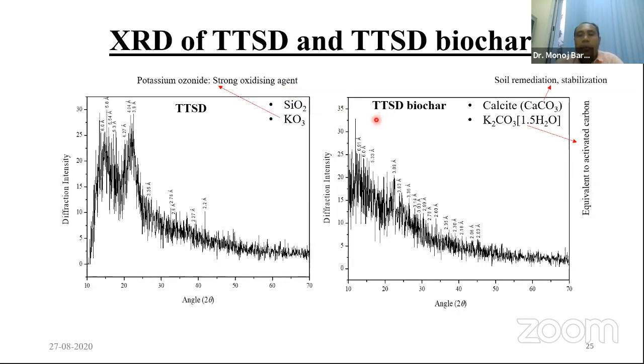And similarly, if we see the XRD spectrum of the biochar obtained from this TTSD biomass, then here again we do not have any crystallinity nature. So this is basically the amorphous kind of nature, and also based on some peaks obtained at different d-spacing values or different Bragg's angles, we can identify some elements, something like calcite, which is very much useful for soil improvement if we apply it for agricultural purposes, like on the soil, because it helps soil remediation, or it can stabilize the soil, and something like this.